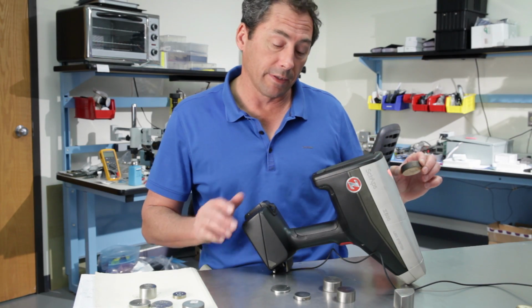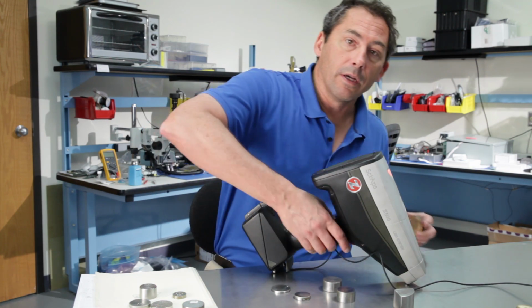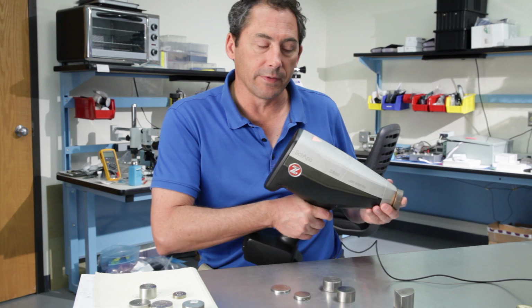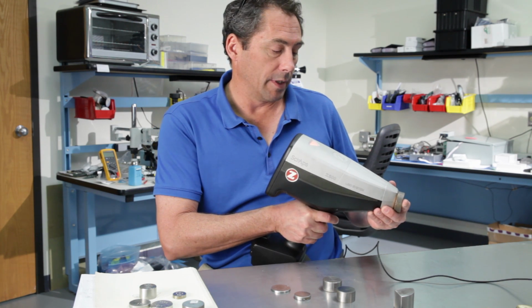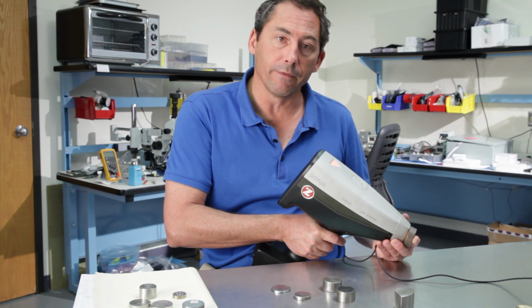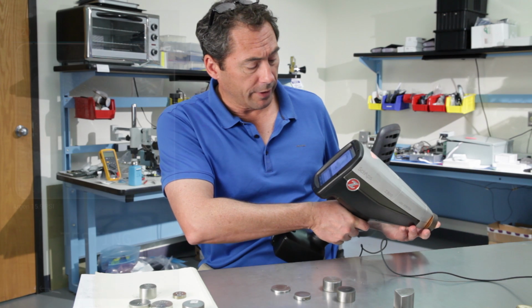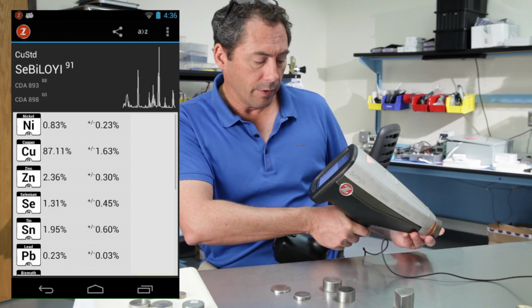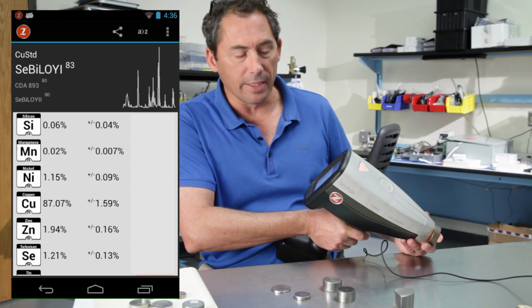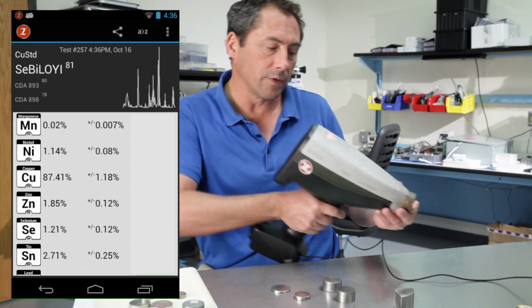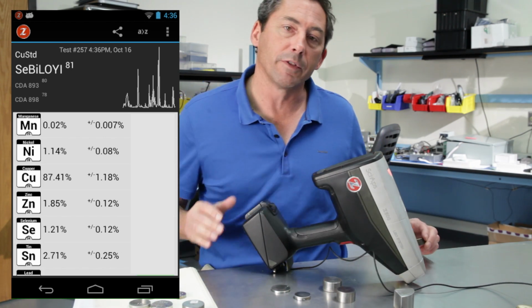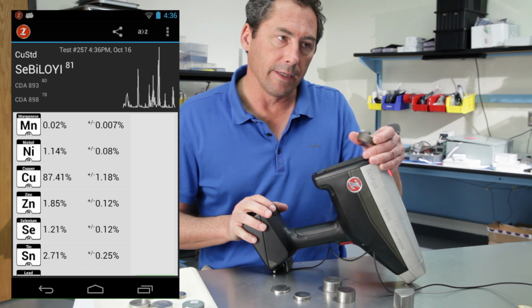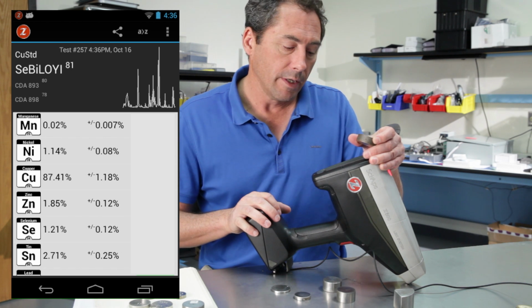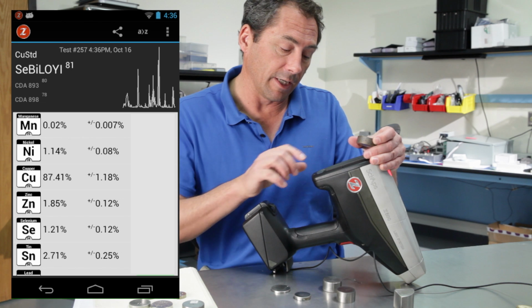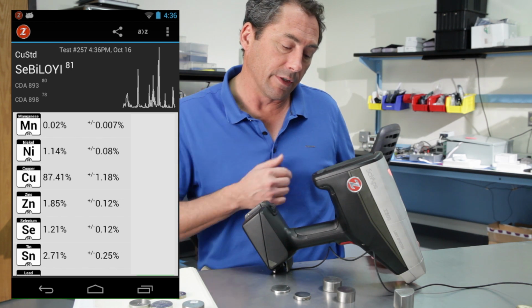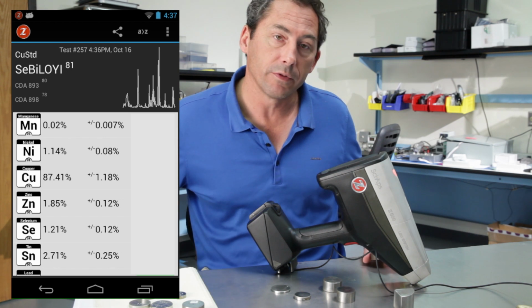Another one I like to show, because it's quite specific to this analyzer, is a lot of these enviro-friendly brasses. These are the brasses that now include either selenium or bismuth or both instead of lead typically. And the thing that's good to point out with this is you need a spectrometer. The best selenium lines are down around 190 to 193 or so nanometers. Those are the best selenium lines to use. So the LIBS analyzer you're using really has to have a spectrometer that goes down to about 190 nanometers. And this is one of the few, perhaps the only one, that goes that low. And you need argon to really get down there and do a good measurement, because those good selenium lines are down there. As you can see, that was a few seconds test, and you can see the 1% or so selenium that was picked up.